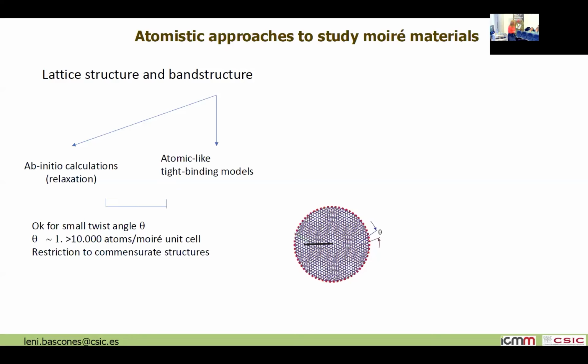So it becomes really big calculations. You can imagine how many theory papers there are on twisted bilayer graphene, and in particular magic angle twisted bilayer graphene. I think I have seen one paper in which they do ab initio calculations for the magic angle. Okay, so this is normally done if you have smaller unit cells. So it seems that it's possible because, as I say, I have seen it in one paper, and maybe there is some other, but not much. Well, of course, the good thing is that you get the atomic positions. And one thing is that in that case you are restricted to commensurate structures, which in other situations can be released.